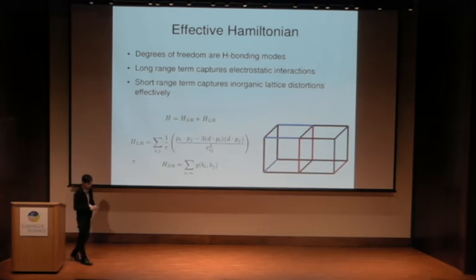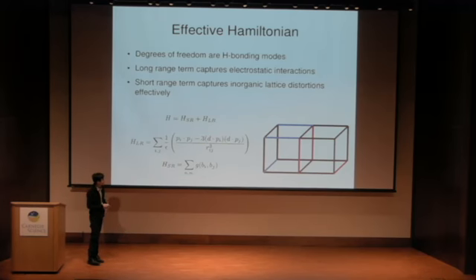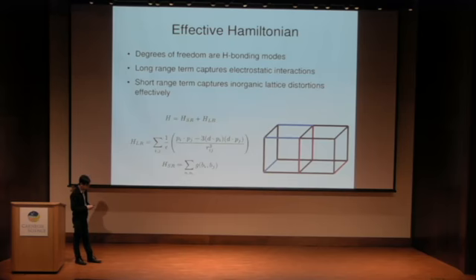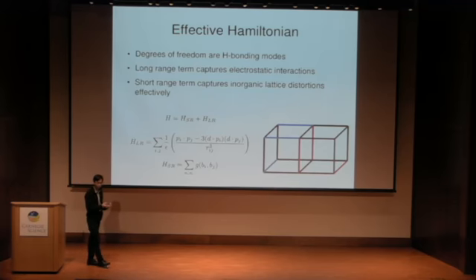Now, finally, I would like to explain how we can construct an effective Hamiltonian from what we've just learned. Since the molecules are dipoles, they have a dipole moment. There should be a term in the effective Hamiltonian which is an electrostatic form, and this part shouldn't be surprising. But there is also a short-range term which comes from a coupling between neighboring molecules.